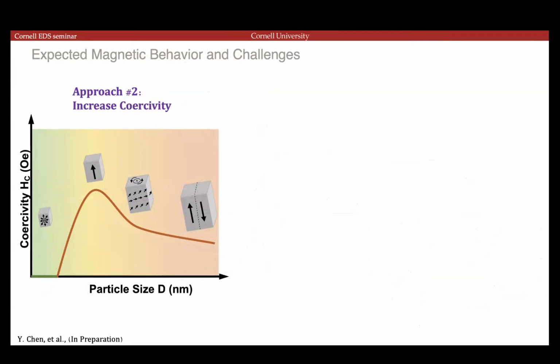So at very small particle sizes, your particles become superparamagnetic. So what I said is they're thermally unstable. Their magnetization is rotating as a function of time, and it's hard to track down. But if you increase it, you'll get to that single domain sweet spot. But if you make the particles just a little bit larger, then all of a sudden they want to cancel that magnetization on themselves, and the magnetization starts to curl and then eventually break up into multi-domain. So in this multi-domain case, there's net, again, zero magnetization because the different magnetization regions are canceling.